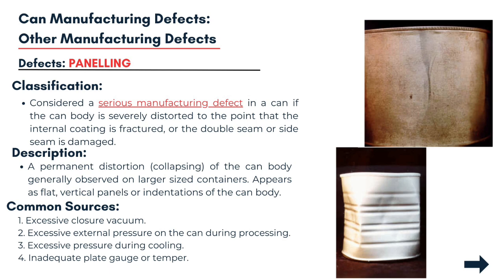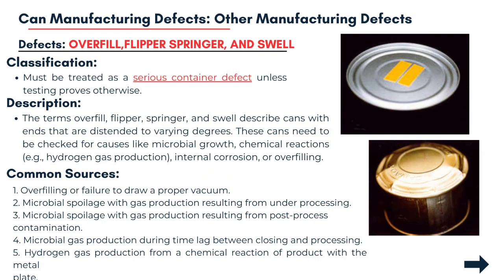There are several factors that can contribute to this defect, including the excessive closure vacuum created during the sealing process, the excessive external pressure exerted on the can during processing, the excessive pressure experienced during the cooling phase after processing, or the use of inadequate plate gauge or temper in the can material. We have other can manufacturing defects. It is overfill, flipper, springer, and swell.